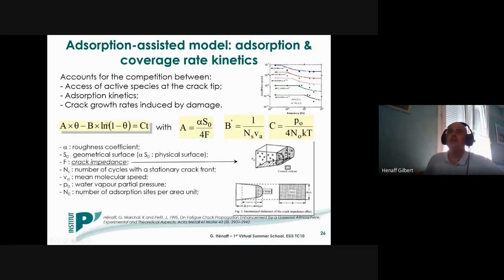And finally, we obtain this equation, and by solving this equation, we have the variation of theta as a function of time that we can then introduce to predict the value of d star and to predict the fatigue crack growth rates, as I mentioned before. What is important to note here is that in these equations, especially for the access of active species, we take into account the crack impedance effect, which is due to the fact that here